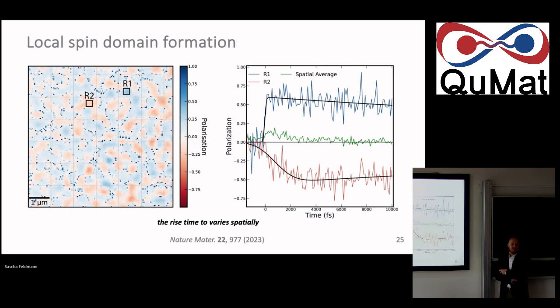Okay. Now, if you summarize over all of these pixels again together to retrieve the macroscopic response that has been previously shown by other people, we retrieve the green curve here, and that was very reassuring to see. It retrieves our macroscopic response. Within 2 or 3 picoseconds, the global response has decayed, it's over. But you see that locally, actually, we outlast for quite a while longer. And you would have missed it had you only averaged over the ensemble.